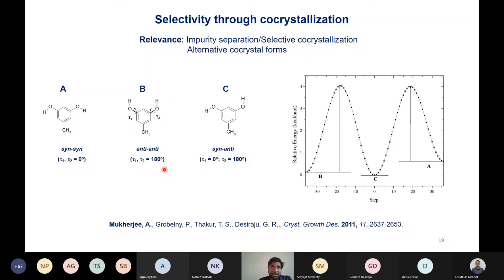And when we tried co-crystallization on those compounds, the purity of the compound improved significantly, which could not be achieved through any synthetic procedure. So impurity separation could be an application of this topic, which I'm going to talk about. You have structurally similar molecules, and one is the target and the other is the impurity. Many times the impurity incorporates into your crystal structure because during crystallization it doesn't discriminate between the two molecules. It's so similar. So co-crystallization can be a way to discriminate between these two.